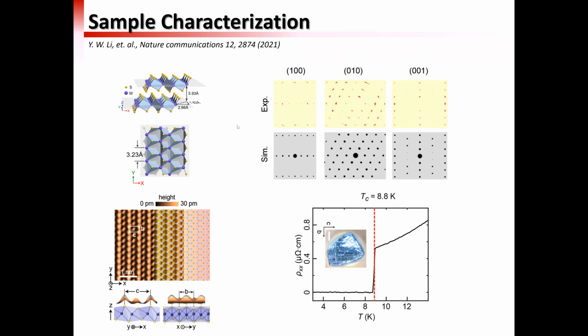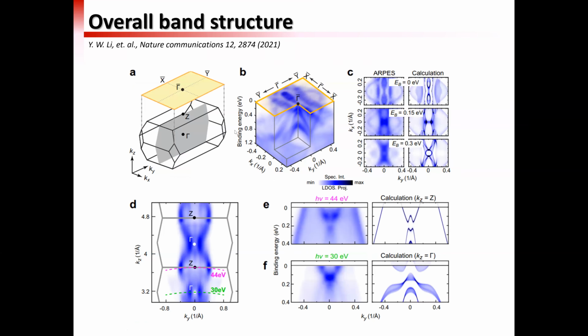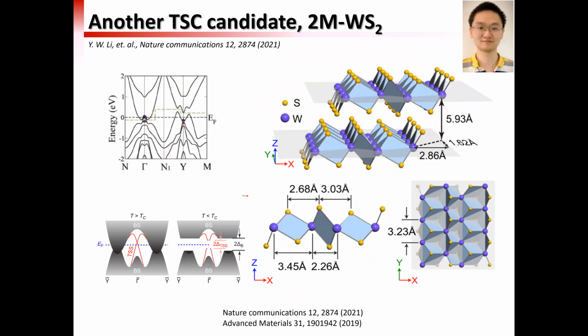Yeah, a lot of those transition metal chalcogenides have a CDW or other surface reconstruction, but luckily this material doesn't have that. And the bulk structural measurements show that the phase is correct. So then we just carry on the ARPES measurement on this material, and you can see the band structure is quite one-dimensional, because the Fermi surface is quasi-1D, plus some 2D pockets here, because it's more two-dimensional than the previous candidate, tantalum triselenide.